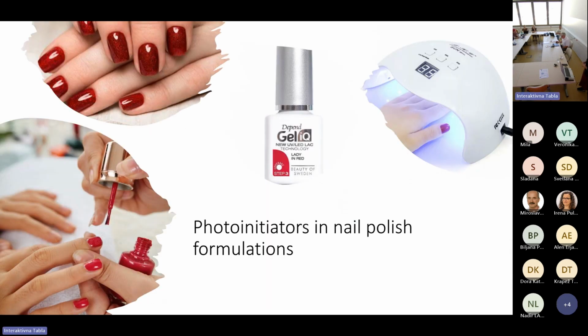Yeah, the next slide. So we use photoinitiators in combination with oligomers and polymers in nail polish formulations. Yeah. So after exposure of this formulation to UV light, monomers and oligomers start to polymerize, and this film gets hard, but not on the top. The top layer remains sticky and unreacted. That's because of oxygen inhibition of the upper layer. Yeah, and this layer has to be then removed.